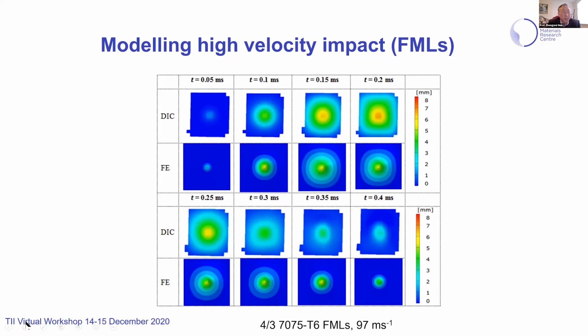This one is the modeling of high velocity impact. We have a DIC displacement field, and then we have the FE simulation. We say reasonably good correlation, but this is just the displacement at different times. This one starts to bounce back, so we also see some recovery in the displacement.